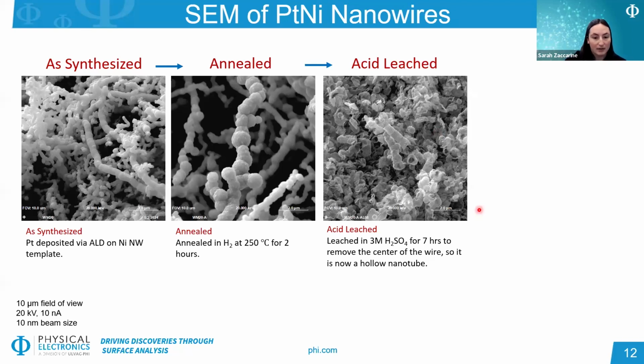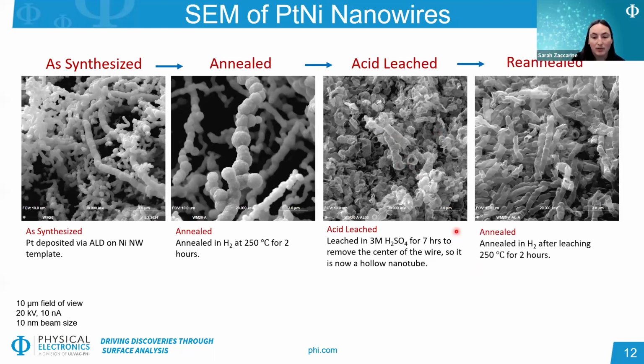We still retain some of this nanowire shape and dimension, which is what we want in order for these to perform. After reannealing, again, they're still hollow. We see it looks slightly more smooth in certain areas, and generally we still see this nice wire structure. And this reannealing step was aiming to use the hollow structure for durability, but also regain some of that platinum nickel alloy, which again, we're going to talk about a little bit later. But generally, the good news is these remain intact. We still see some of that nice morphology and structure even after all of these different processing steps.